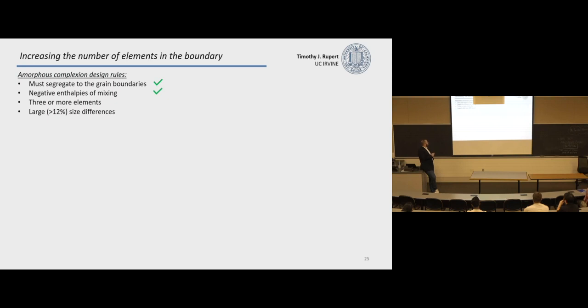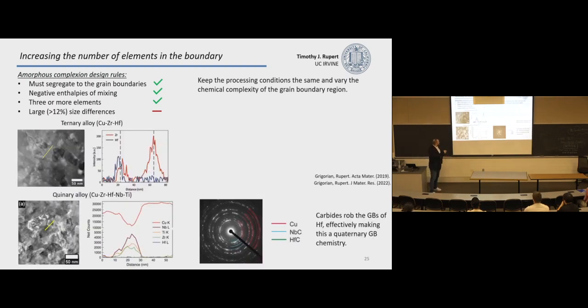So we can start to test those other things. So I mentioned that these first two are required, you have to have them. We can start to see how these other two can affect things. So first I want to show you what happens when we add in 3 or more elements to the grain boundary. So I'll make a ternary alloy, copper, zirconium, hafnium. I'll make a quinary alloy, copper, zirconium, hafnium, niobium, titanium.